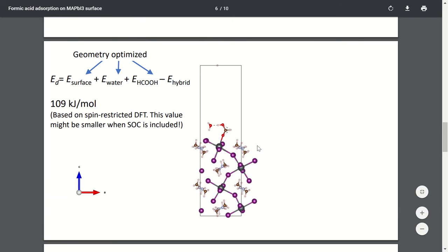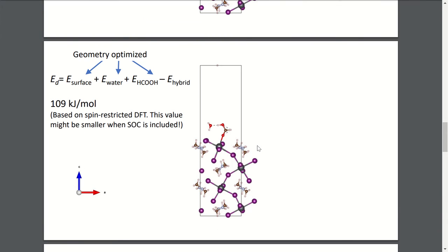Next I tried putting water. And this is very, very stable, I guess. The binding energy is like 110. Here, we still have the oxygen-metal bonding, and this is the water, so it forms a ring structure. This is one member of the ring, this is one atom, second, third, fourth, fifth, and sixth. That's the reason why this geometry is very stable.